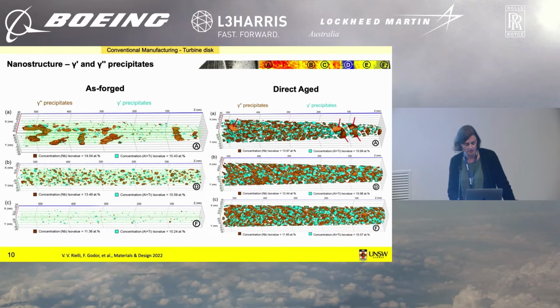So in the next step, here you can see some atom probe microscopy, so that's real nanoscale information of forged positions from this disk. And what you can see here is a slight decoration of the microstructure with nanoscale particles. So there's two kinds in this alloy. One are called gamma double prime precipitates, they're rich in niobium, and the other ones are called gamma prime, the turquoise ones.